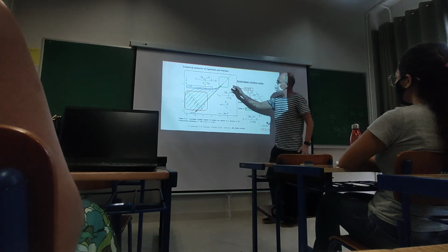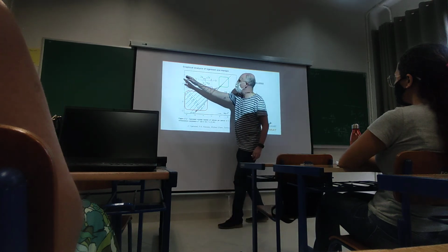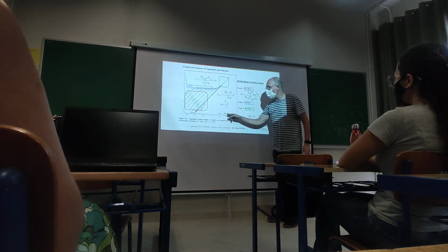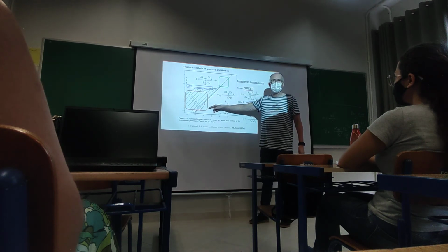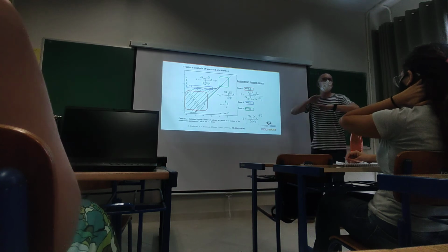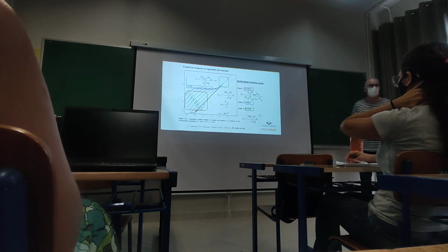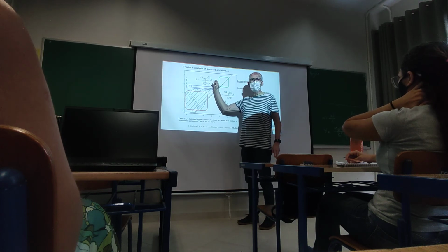So this is the solution, and here now what you have is M bar as a function of alpha for different values of N and for a single case which is no termination of radicals in the aqueous phase. So the radicals do not terminate in the aqueous phase because Y is 0.